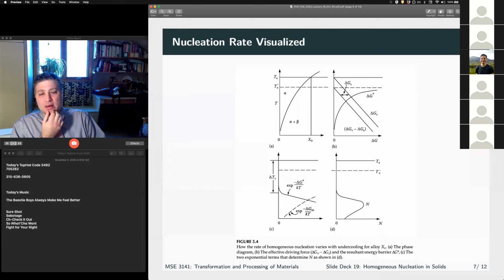Okay. But what happens to diffusion with temperature, right? Our ability to move atoms is much higher at higher temperatures and low at low temperatures, right? So our driving force for the phase transformation increases with a bigger undercooling, but our ability to move the atoms decreases with a big undercooling, okay? So if we're up near the equilibrium phase transformation temperature, we have a huge amount of mobility, right? We can easily move atoms around, but we don't have enough driving force to overcome our activation hump. So we have a very low nucleation rate, right?